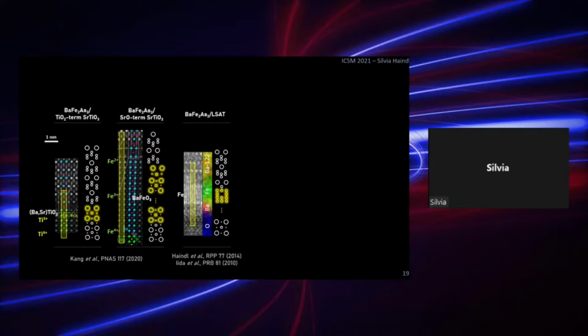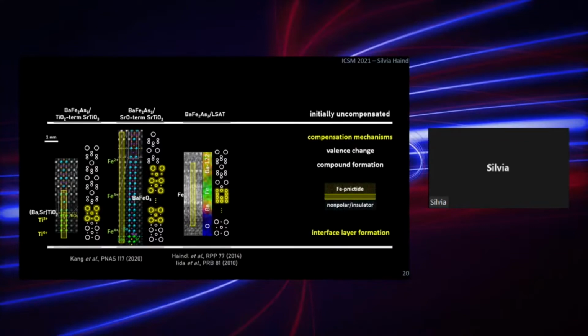So we can summarize all these examples as hetero interfaces where we have interface layer formation, and we can call them initial uncompensated interfaces. That means the interface tries to compensate the layer charges and the dipole moments, and this is done via the valence change, the compound formation, or via the metallic iron layer. So the question is, can we also have clean interfaces?